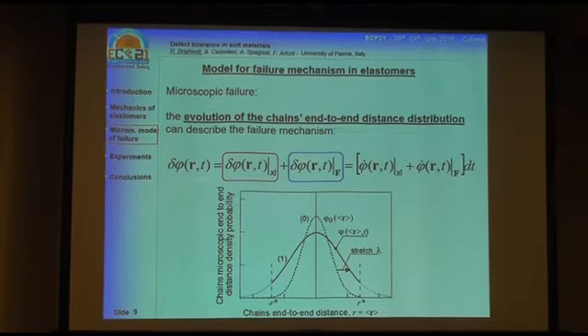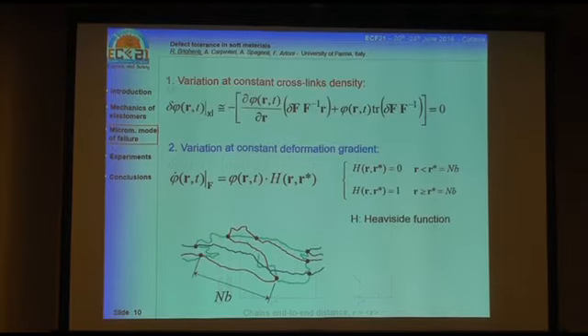So the total variation of the distribution function can be written by using a first part, which is related to the cross-links existing in the material. We don't take into account this term here because we don't consider, for example, degradation of the material, but only the variation due to the deformation that we are applying to the material. So delta phi f is the only contribution that we are considering in this model, but we can also add more contributions in case we have this aspect. So our variation is written in this way.